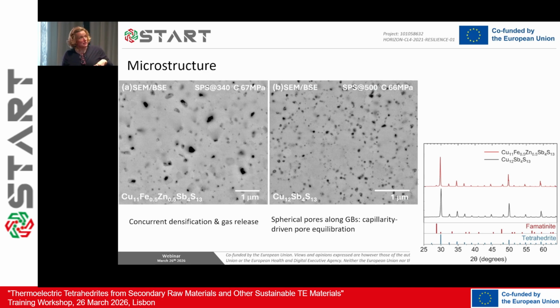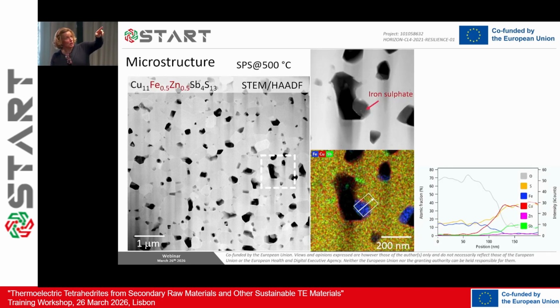So if you look at these samples, the iron and zinc doped ones, this one was produced at 500. You see very big pores, in this case larger than the ones before, I'll explain why in a minute. What is important here is that in this case you have a magnification of this large pore, and there's something in there.